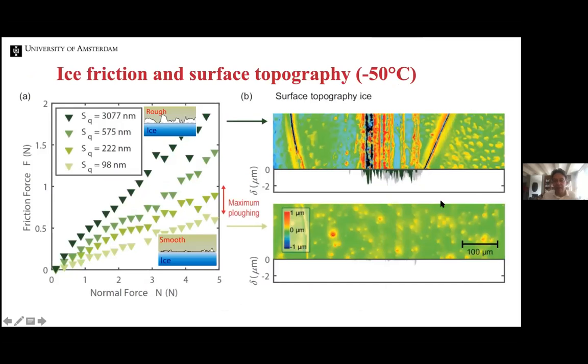The fact that it's difficult close to melting is easy to understand. If you have a rougher skate, you will actually plow more, and the plowing is difficult. And so this is a profilometry image of the ice after a rough skate has passed. And you see that you leave really very deep traces in the ice.